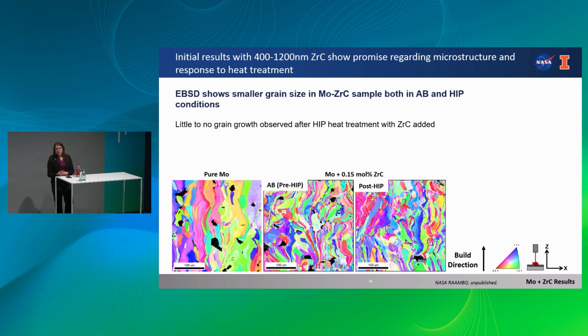The biggest thing that we found, though, is that adding these nanoparticles actually helped reduce the grain size. As you can see, we did as-built EBSD as well as post-HIP on the smallest amount of added zirconium carbide. And as you can see here, the grain size is much smaller than even the as-built pure molybdenum. This is promising because not only are we getting these smaller grains during fabrication, so even though we do see some porosity, we probably are reducing our actual cracking, but also this reduced grain size after hipping is good because now we're not getting this large grain growth,